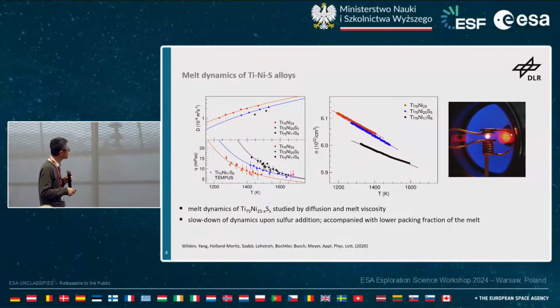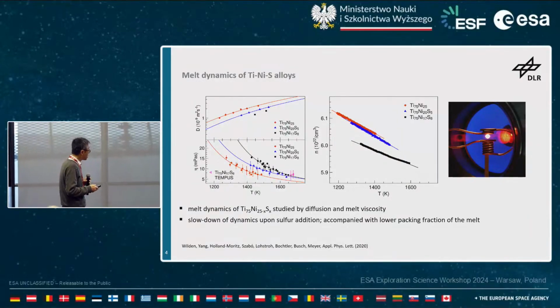We measure the density and translate that into the atomic number density in the melt. And what you see is that they are slightly decreasing, which means that your melt actually gets slightly more loosely packed, if you want. This shows you again that the sulfur has a special effect. It's not like a standard or conventional alloying element. So structurally there must be something going on.